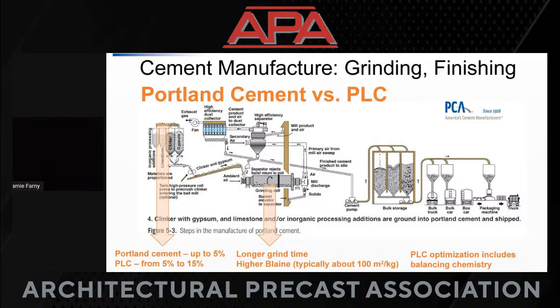So we speak about the fineness of Portland cement as a Blaine number typically. And with a Portland cement versus a Portland limestone cement, we're going to be increasing that Blaine by about 100 meters squared per kilogram. So it is a measure of the surface area to the mass of material. Most Portland cements are going to be in the upper 300 to low 400, maybe mid 400 range. So the Portland limestone cements are going to be in the mid 400 to upper 400, over 500 maybe range of fineness.